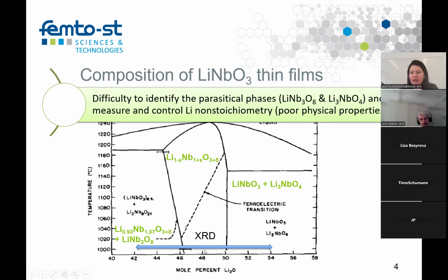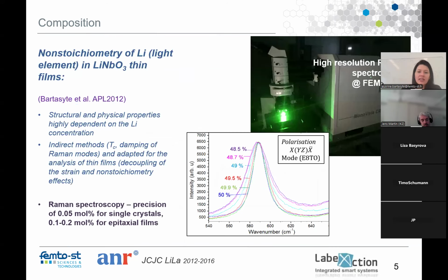So I cannot confirm that my film is exactly here. And there are also some orientations where, for example, your parasitic phase has exactly the same position of X-ray diffraction reflection as your lithium niobate. So this is, for example, the Y-cut orientation. You almost never see the parasitic phases, even if there are plenty of them, because your X-ray diffraction peaks superpose on each other. So X-ray diffraction is not an adapted method. Another thing is that lithium is a very light element, and you cannot measure the composition directly, especially with such precision.